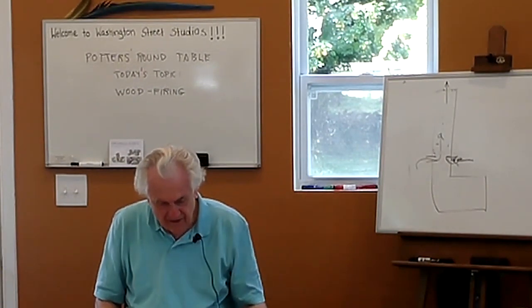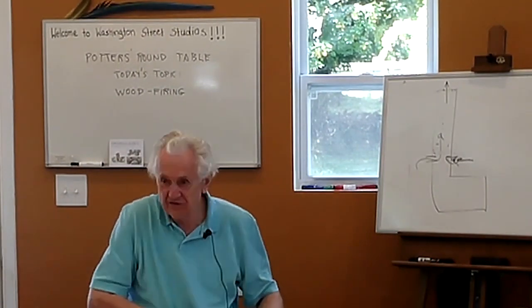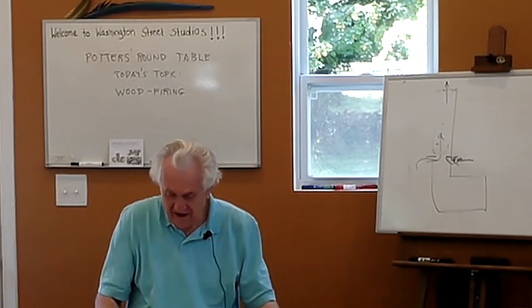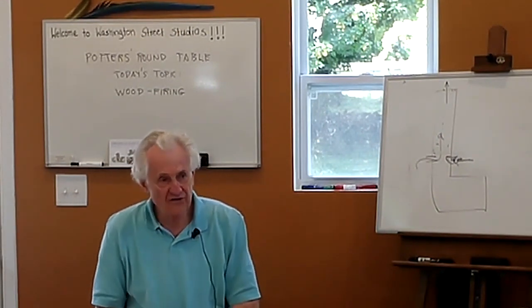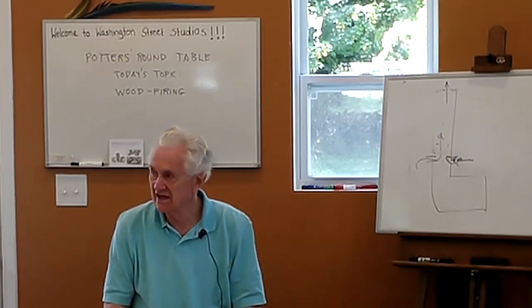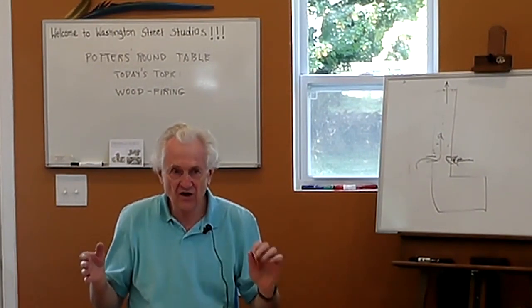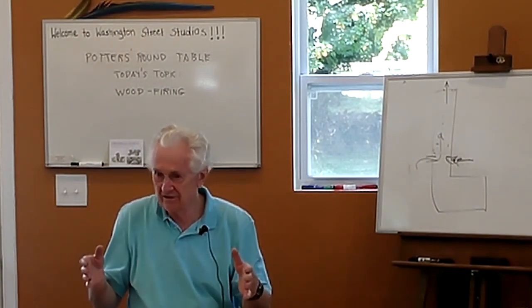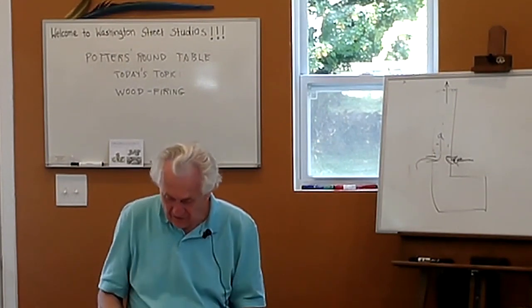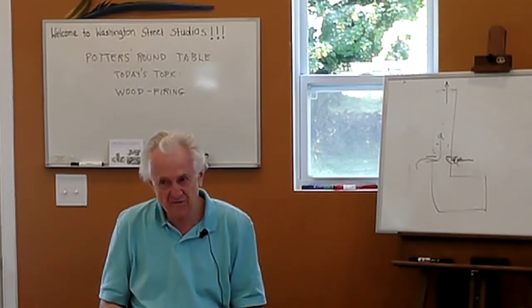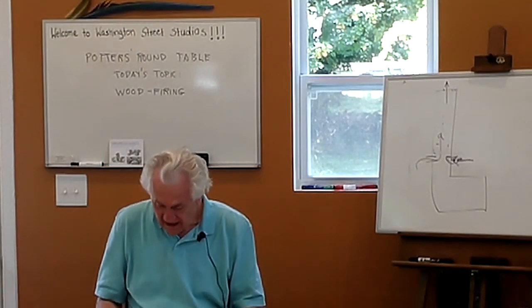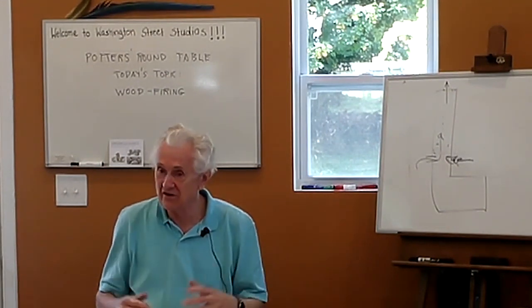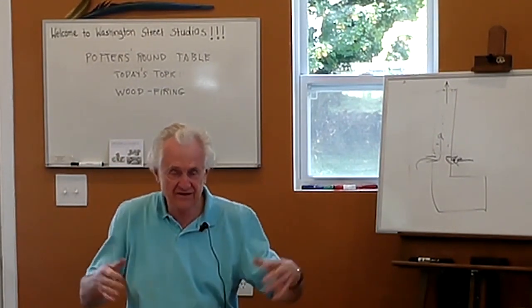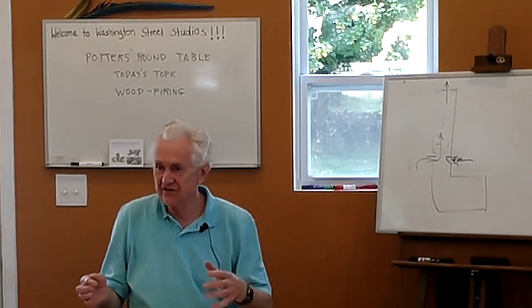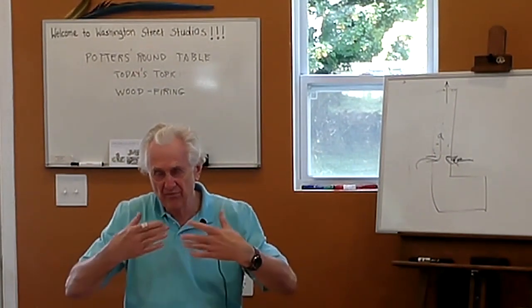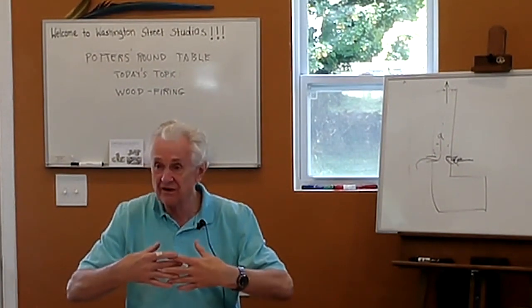Another problem is hot and cold spots in a kiln, and this is very common with wood. It also is very common depending on the kiln design, that with any kiln, it's hard to get uniform heating of the whole ware chamber, and it really is influenced by the kiln design. And it's also influenced by the stacking, because as I mentioned before, once you've got your kiln built, you're done with the kiln design. But there are things you can do in terms of stacking and other little barriers and things you can put inside to redirect the flame.